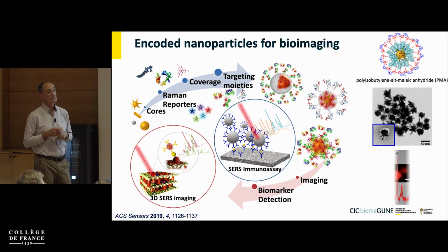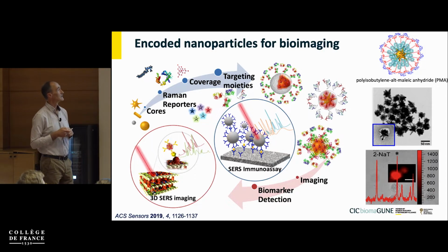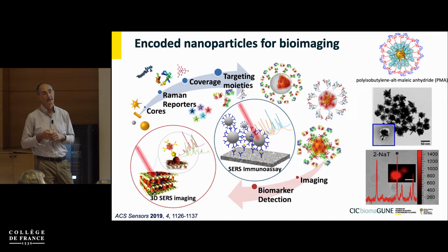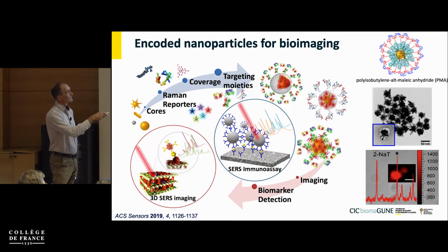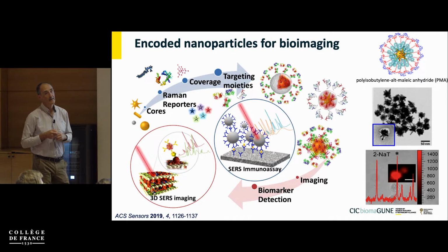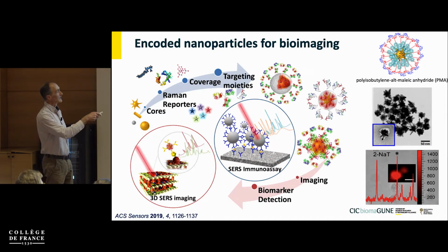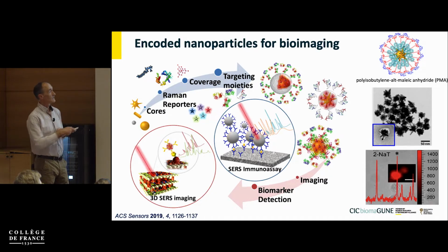Nowadays we typically use this strategy, which is sort of adapted from my initial work in the group of Wolfgang Parak. Basically, our trick is now using hydrophobic molecules which have a rather high Raman cross-section, like those with aromatic groups, carrying also a thiol that will bind to the nanoparticles. So these nanoparticles will become hydrophobic.